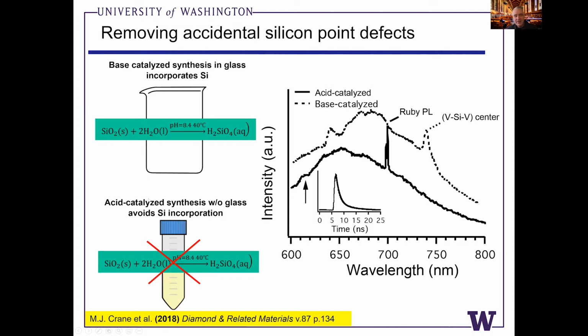So we had an idea. Matt Crane led this effort, and effectively what we did is just switch to plastic glassware. It was a really simple fix. And instead of working in water, we started working in an organic solvent that was acidic instead of basic and had much faster gelation. And you can see in this comparative spectrum, the dash spectrum is what we had originally. And simply by switching to the plastic container, we completely got rid of the silicon split vacancy peak. It completely vanished.